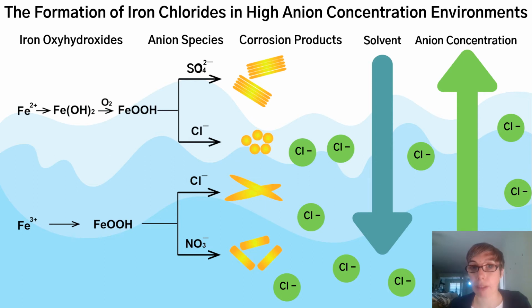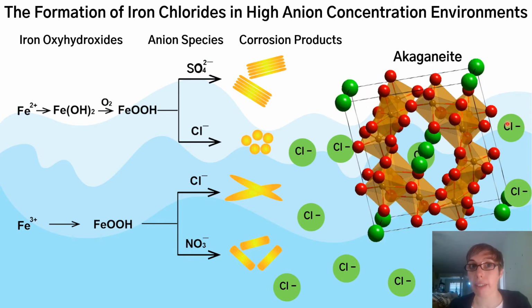In contrast to copper chlorides, which begin their formation in the burial environments, many of the most destructive forms of iron corrosion are iron chlorides, which form largely in the post-excavation environment as artifacts begin to dry out and water evaporates. This is because iron chlorides are very concentration dependent. They can only really form as that water evaporates and the solute concentration of the chloride ion goes up. An example of this is akaganeite, which is a corrosion product that actually incorporates chlorides into the crystalline structure. They're actually inside and part of the structure, and they also tend to attract chloride ions onto the surface as well.